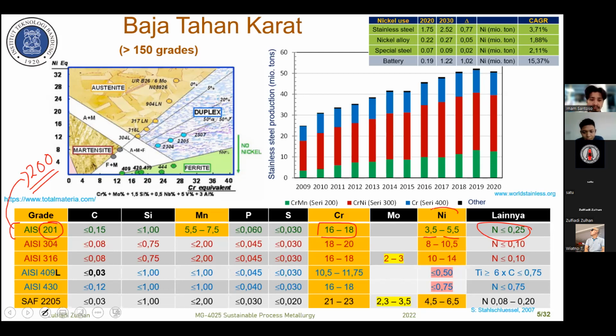In this case, most of the nickel is substituted by manganese. We increase the manganese content because manganese, like nickel, is a stabilizer for the austenite phase. So if we add more manganese, the phase in the steel will be austenite. So for the 200 series, most of the nickel is substituted by manganese. The largest portion of stainless steel produced worldwide is austenitic, the 300 series. The most common is 304 stainless steel. For this grade, the nickel content is around 8 to 10.5%, and chromium is 18 to 20%.